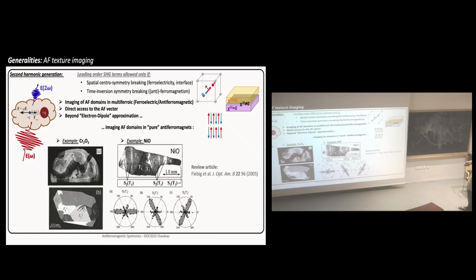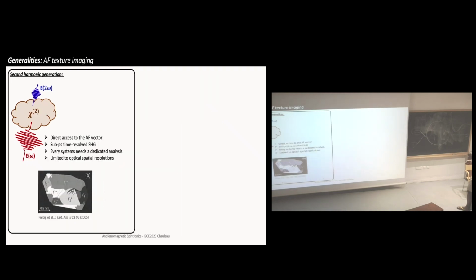All this is work from Manfred Fiebig. This has been shown in Cr2O3, so it's a more advanced way of doing second harmonic generation, but then you have direct access to the Néel vector, to the antiferromagnetic vectors. And here, for example, it's in the prototypical NiO. This is the same, with the nice thing that you have direct access to the antiferromagnetic vector. So just to sum up on this one, it's a direct access to the antiferromagnetic vector.